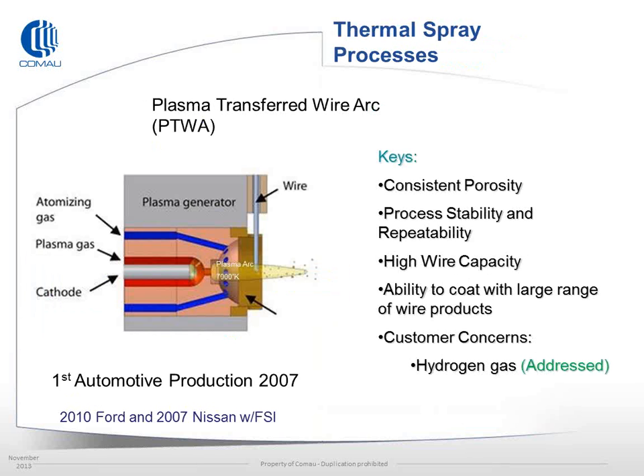In plasma transferred wire arc, we have an arc temperature of roughly 7,000 degrees Kelvin. We use a cathode to create a plasma field between that and the anode, which we use as our consumed wire. We don't use this for propulsion. It's only used to melt the tip of the wire. What we have is an ionizing gas stream, which is the blue lines that you see coming in through multiple orifices around the plasma field. This is what creates the atomization and the acceleration of the particles towards the surface.